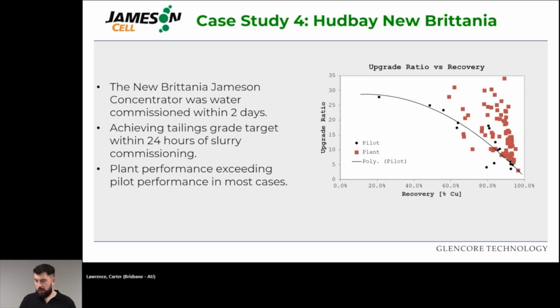Now, what was very impressive about New Britannia is that the concentrator was water commissioned within 2 days. Now, anyone familiar with commissioning a concentrator, it's often a very slow process, can be quite difficult. So to have it fully water commissioned within 2 days was very impressive, and the Hudbay team were very impressed by this. Now, within 24 hours of slurry commissioning, the tailings grade target was being achieved in the plant. So again, very fast ramp up and minimal optimization required.